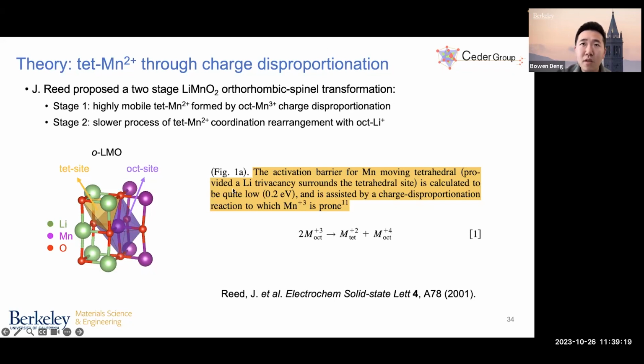And the hypothesis is made this way since in a quasi-static NEB calculation, the manganese 2+ ions are shown to have a low migration barrier compared to manganese 3+ and manganese 4+. So that's why John Reed made this proposal that it's only through the formation of manganese 2+ that these manganese ions are able to migrate at a surprisingly high speed during room temperature electrochemical cycling.